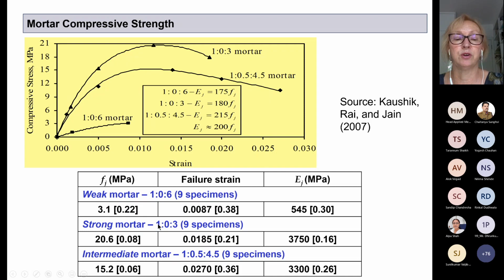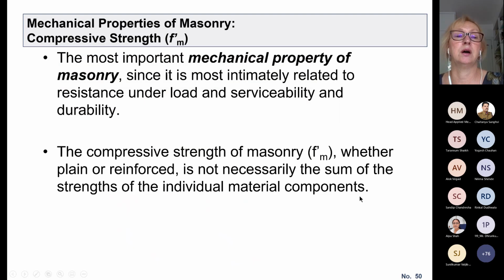Strong mortar, 1:3, has a strength of 20 megapascals, which is about twice the strength that M1 mortar needs. We remember M1 strength is 10 megapascals, and intermediate is 15 megapascals, which is again very high strength, much stronger than required by this M1 type of mortar. So that is important. For mortar, that was all I wanted to say.